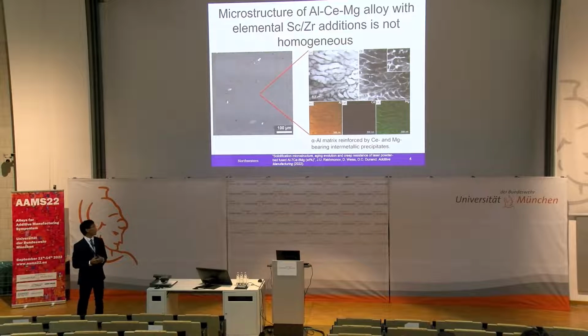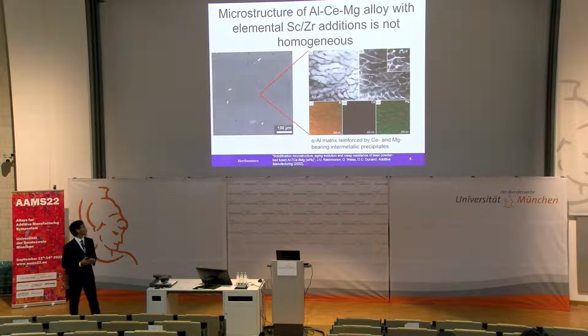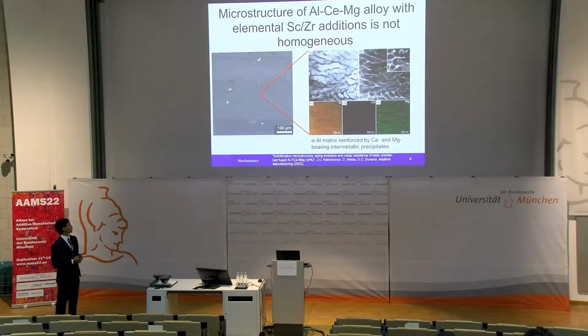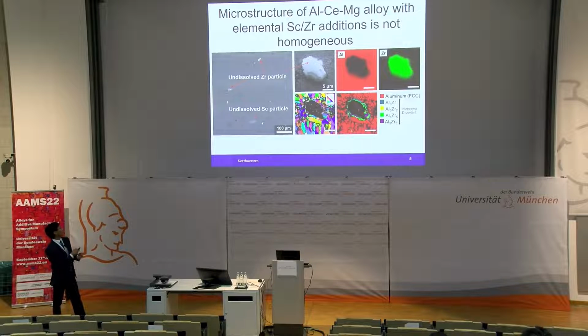So immediately when we print the sample, what we see is that the microstructure is quite inhomogeneous. If you zoom into this gray matrix in the background, what you see is this FCC aluminum phase reinforced by these cerium and magnesium containing precipitates. And this is basically characteristic of the aluminum-cerium-magnesium alloy without any sort of scandium or zirconium in it. Now, when you take a look at these white and gray particles, what we see is that they are indeed undissolved zirconium and undissolved scandium particles.